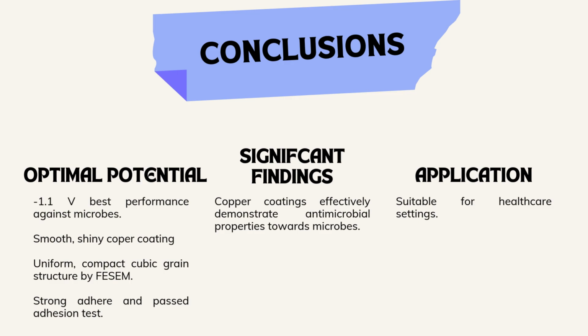As the conclusions, the optimal potential was found to be at negative 1.1 volt as it possessed the best performance against microbes. It has a smooth and shiny copper coating. It also has a uniform and compact cubic grain structure by FESEM analysis. It also possesses high copper content by EDX analysis, and lastly, it has strong adhesion and passes adhesion tests. The significant finding for this study is that the copper coatings effectively demonstrate antimicrobial properties towards microbes, and for application, it is suitable for healthcare settings.